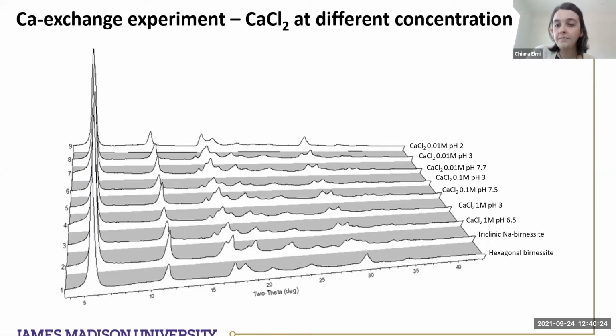So this is another picture of the different molarity. Even with the different molarity, you notice that the exchange itself is not affecting the structure. Mostly it's the pH that is affecting this structure change. So it's mostly related to the acidity of the solution rather than the cation exchange itself.